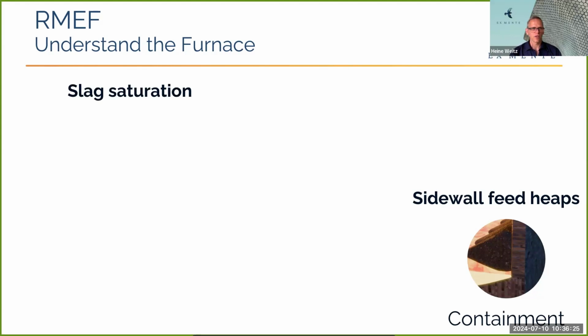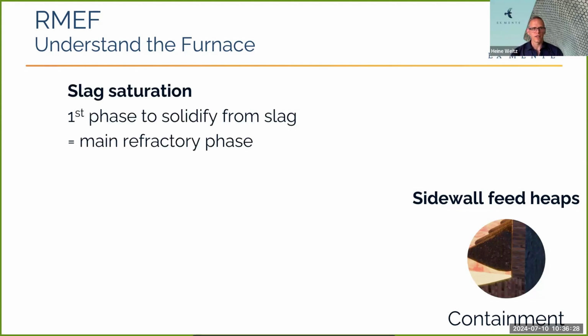Okay. The second containment concept is that of slag saturation. So the idea here is to make sure, or to see if, your slag is saturated in the primary phase of your refractory material. This is practically what that means. We would take a slag composition and perform thermochemistry calculations, equilibrium calculations, on that over a range of temperatures. And we look at the first phase to precipitate upon cooling. If, for example, your first phase to precipitate is periclase and you've got a magnesia-based refractory, the likelihood of that refractory material dissolving into the slag is much lower than if you have, for example, an alumina-based refractory material. So that is one strategy to contain the process.